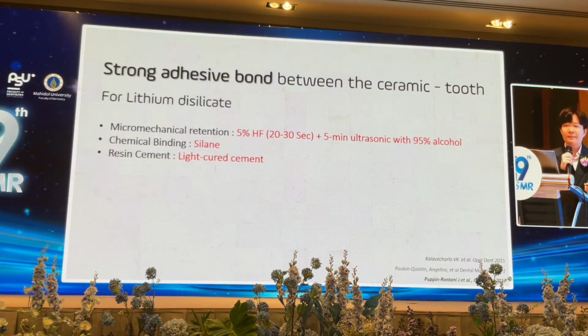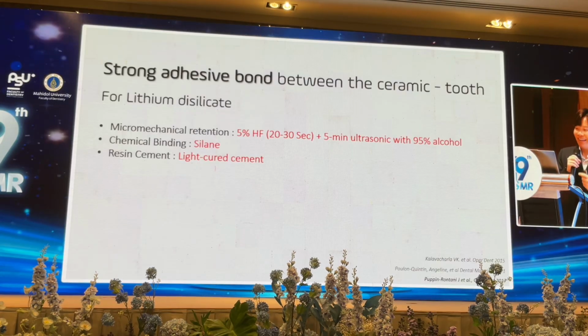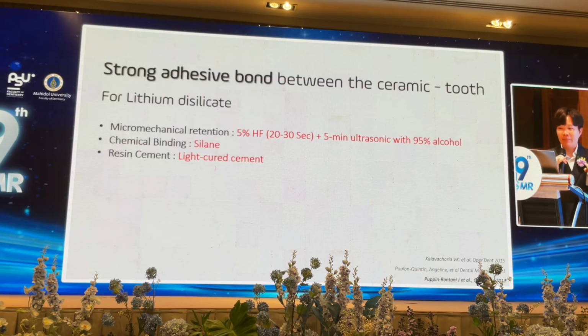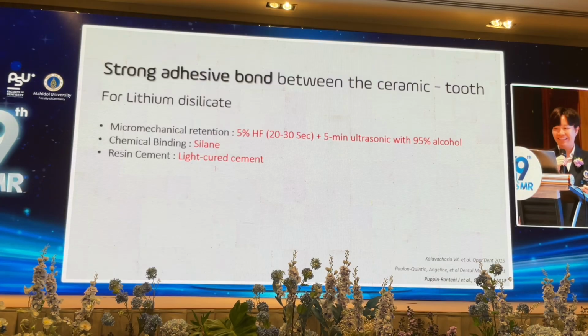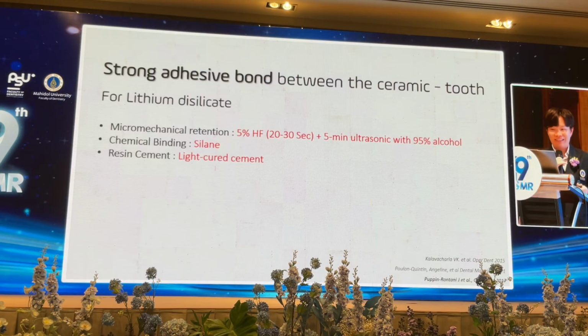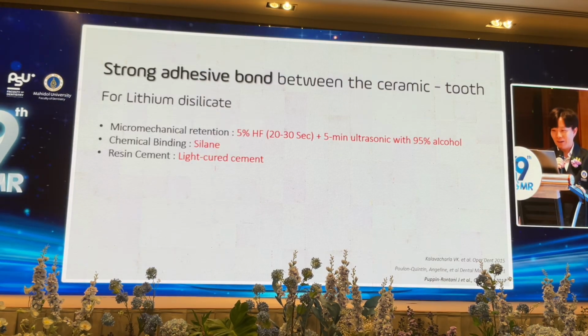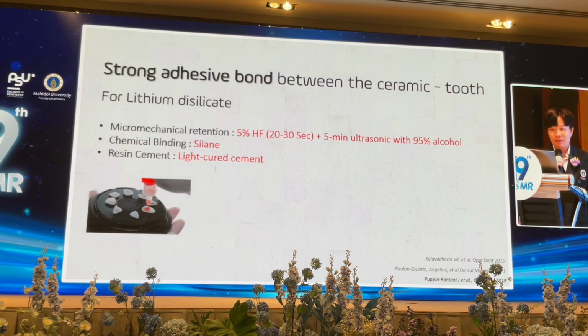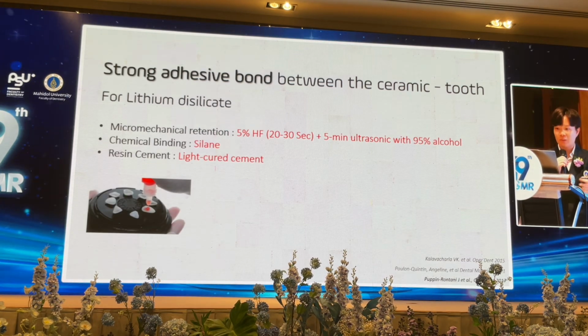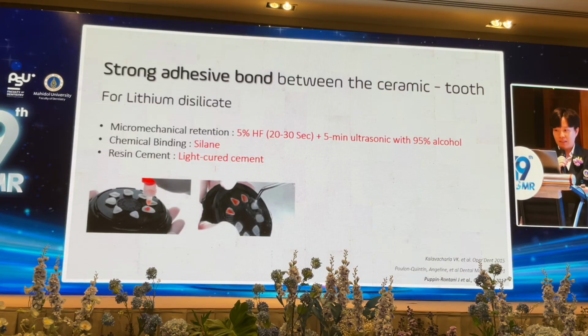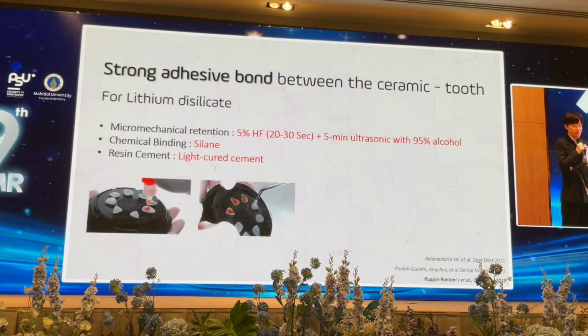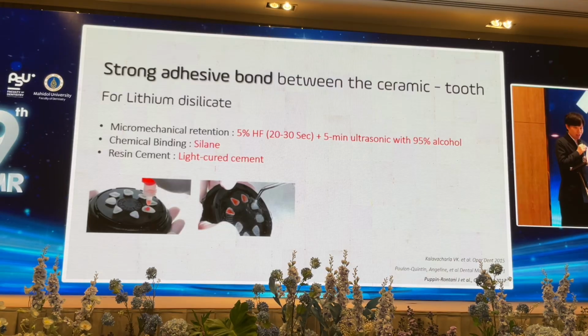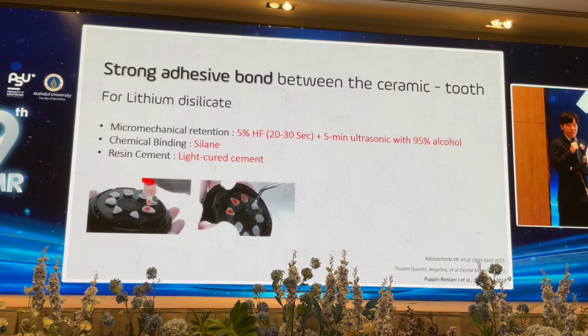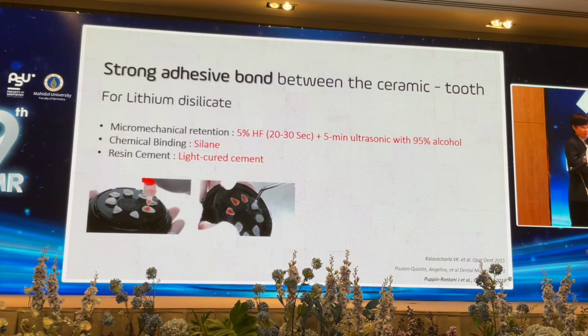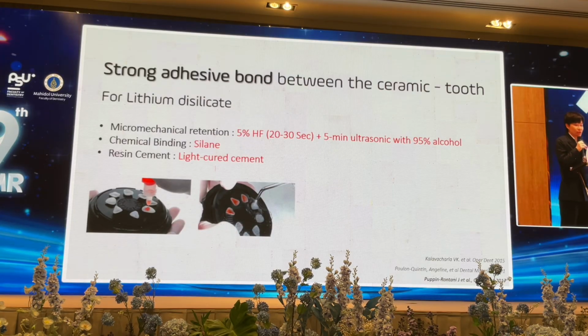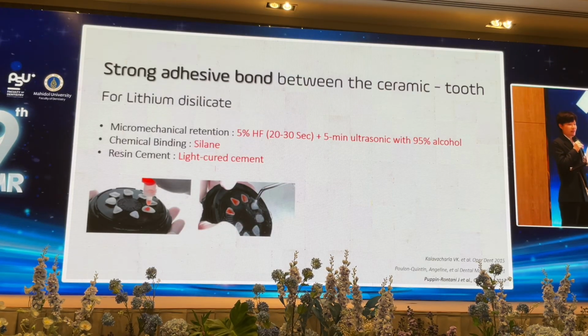And with the limited time again, let me quickly wrap up the entire bonding process for lithium disilicate. I'll summarize it in one slide. For micromechanical retention, we start by etching with the 5% HF for 20 seconds, then rinse it off with the air water spray for 1 minute, or even better, use an ultrasonic cleaner with 95% alcohol for 5 minutes to remove those insoluble silica fluoride salt that can otherwise weaken the bond.